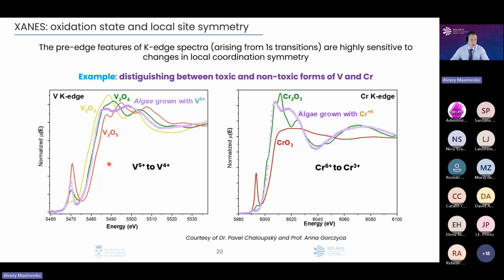And as you could see, we measure what vanadium and chromium we have in such a live organism during its living in such contaminated waters, and we see that this algae could transform toxic vanadium and toxic chromium to non-toxic forms of these elements, just by analysis of the intensity of the pre-edge peaks.